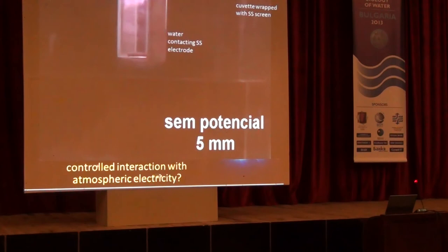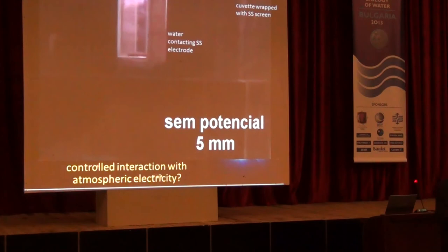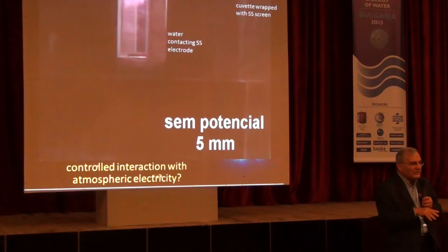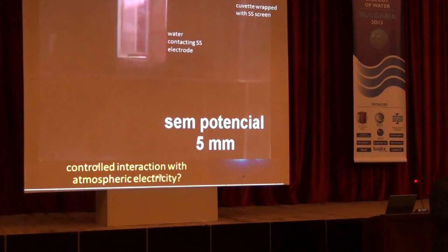Yes. I thank you for asking this question, because it is really essential. There is something that is not known to everyone, but you know Erwin Schrödinger, very important physicist. Schrödinger's PhD thesis was exactly on this phenomenon. He was observing changes in charge dissipation from insulator surfaces, and observed that as you increase conductivity, charge imparted to the surface dissipates easier. And the idea that has been around all the time is that as you increase humidity, you absorb water, that increases the surface conductivity, which helps charge to be dissipated. And that's true. Nothing against this.